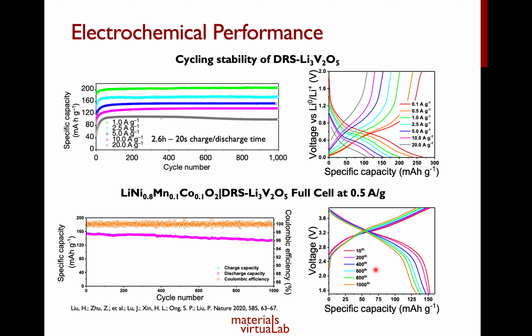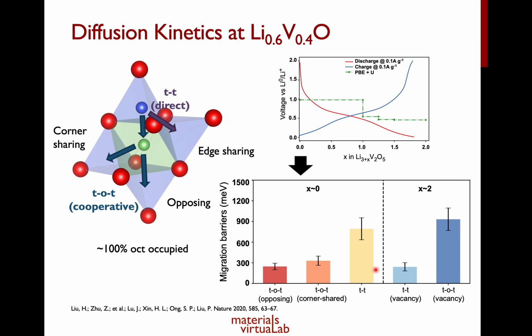So to answer why the electrochemical performance is so good, we actually performed nudged elastic band calculations to understand the diffusion kinetics in the disordered rock salt, both at the start of charge and the start of discharge. So let's start first with Li3V2O5. Just to remember, at this starting composition, we have all the octahedral sites occupied.